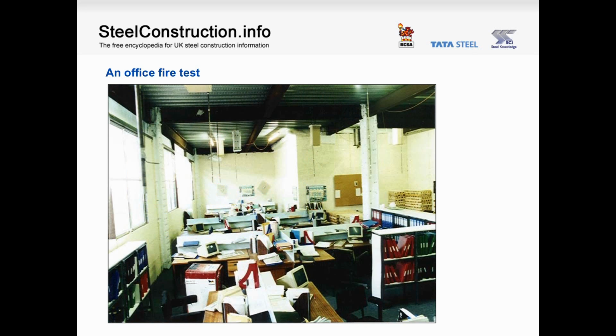The fire load was provided by gas, wood, or in this, the most severe of all the fires, office furniture. In all the tests, the beams were unprotected, and that can clearly be seen in this photograph. The purpose of the tests was to demonstrate that composite steel deck floors had much greater levels of inherent fire resistance than was apparent from fire tests on individual members, and also to try to understand the mechanism by which this occurs so that it could be utilised in design.